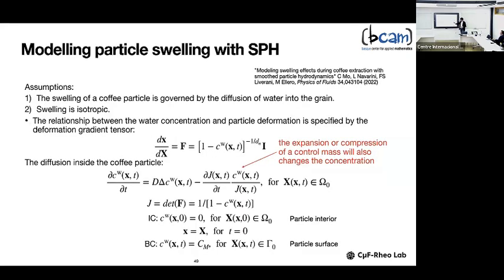In this paper we have introduced a model of the swelling, following the philosophy that we previously introduced for the erosion model: we try to introduce swelling at the level of the single SPH particles. We don't have a continuum model, but we act at the level of the single particle. We assume that swelling is related to the amount of water which is imbibed into the solid phase. So if there is no water, there is no swelling. The larger the concentration of water, what we call here excess water, or you can call it moisture, the larger will be the swelling.